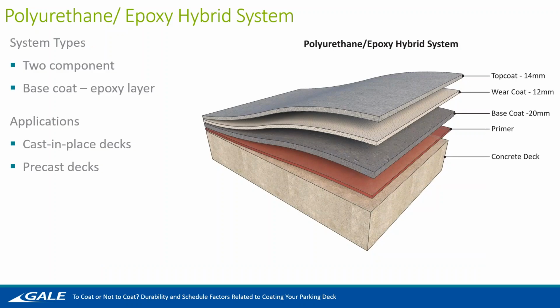So the next system is the polyurethane/epoxy hybrid system. This is a 2-component system. It's similar to the polyurethane system, but a little bit better. The base coat is the epoxy layer, and it has its benefits. It adheres better to the concrete than the polyurethane system. The polyurethane with the wear coat and the top coat is UV stable. So an epoxy system would yellow with the sun beating down on it. And Kat will dive into that a little bit more later.